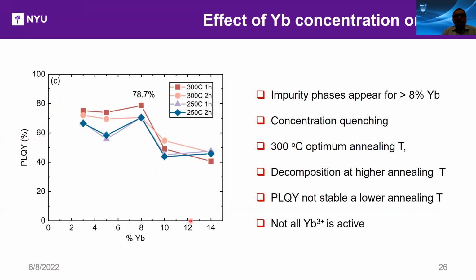Effect of ytterbium concentration on photoluminescence quantum yield looks something like this. Here we show also data for different annealing and different annealing times. The films annealed at 250 degrees centigrade tend to be unstable in air. So when we take it out in the air and let it sit around, its photoluminescence quantum yield changes. So some of these decreases are due to how long we waited to make the measurements, etc. But when you do the annealing at 300 degrees centigrade, we get high photoluminescence quantum yield. It's constant. I'll show you it's stable in air.